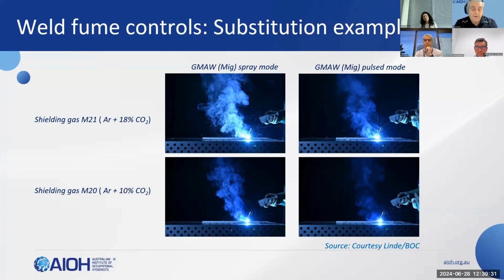Furthermore, it has been established that the level of carbon dioxide in the shielding gas can also have a profound effect on the amount of fume generated. Now, reducing the carbon dioxide content from 18 to 10% in this particular example can nearly halve the level of fume generated. Obviously, it's not going to eliminate it if you get rid of all the CO2. But it should be noted, though, that reducing the CO2 content of the shielding gas may not be feasible from a technical perspective, as it can adversely affect the weld metal properties and classification of the welding consumable. Watch this space, however, for future developments, no doubt.